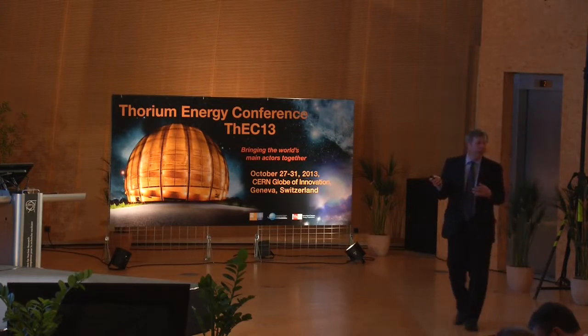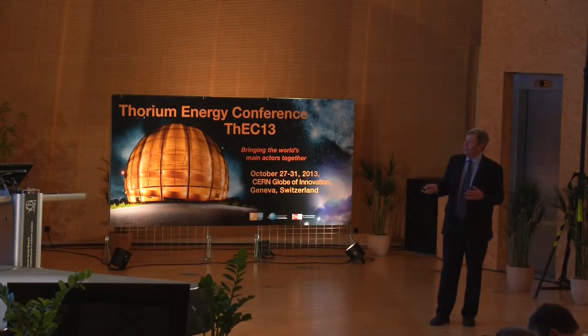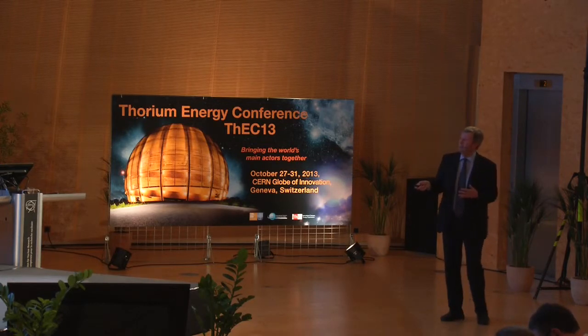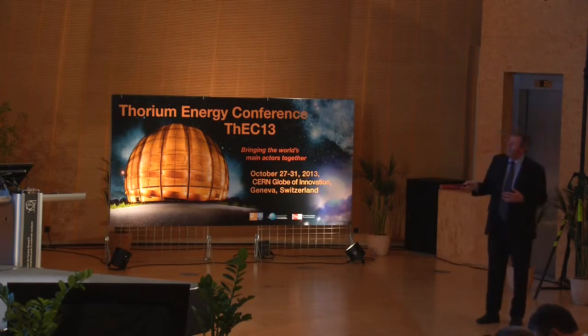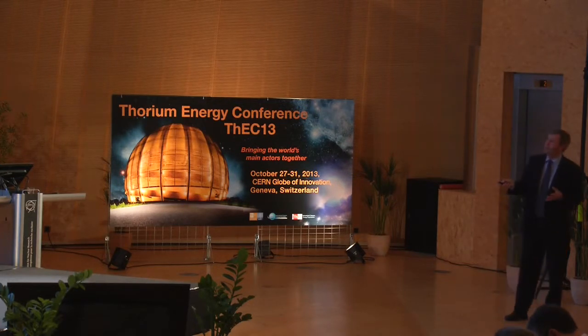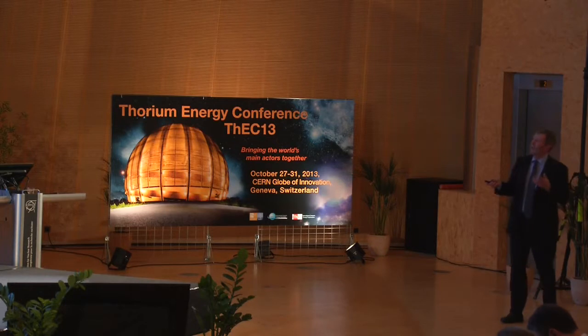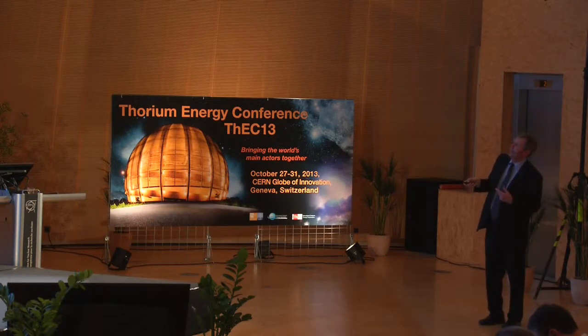So one can perform this interpretation and link the behavior, the observable properties, to the underlying atomic scale structure to provide an interpretation of the behavior of different materials. So this is our favorite fluid here, FLiBe, or lithium fluoride, beryllium fluoride mixture. And at this composition, it's equimolar lithium fluoride, beryllium fluoride. And again, you can look at these coordination motifs here, where in this case, because a beryllium ion is a lot smaller than a thorium one, each beryllium ion tends to be surrounded by about 4 fluoride ions in a kind of tetrahedral arrangement. And you can decorate your tetrahedra there in this way. And now you can see that the liquid is really this kind of network of interconnected tetrahedra. They're connected because a pair of berylliums here share a common fluoride, so that their coordination tetrahedra get linked together.